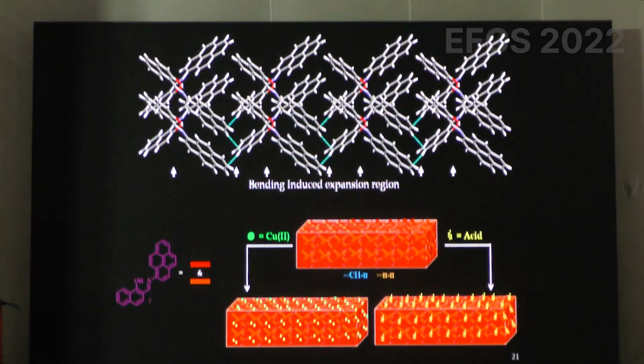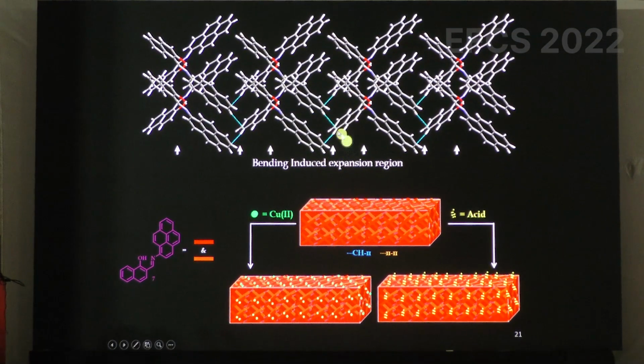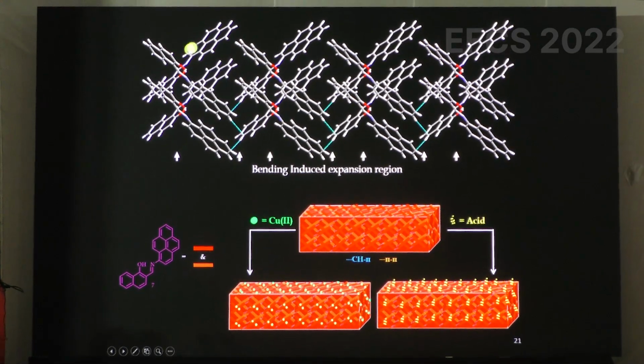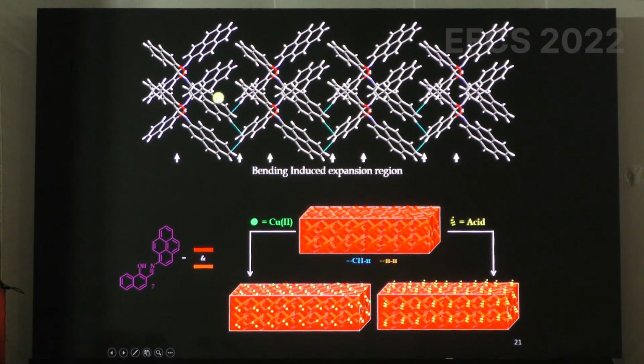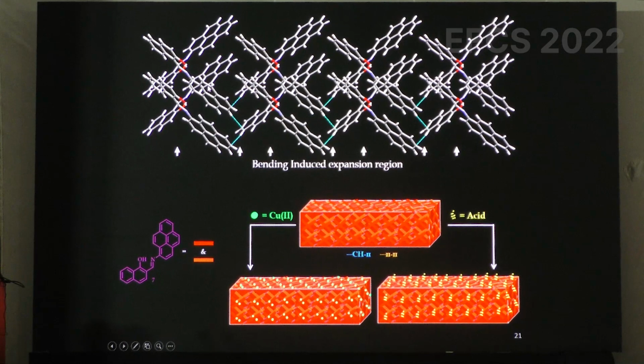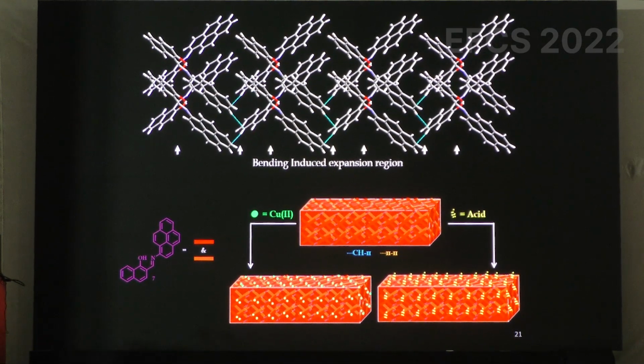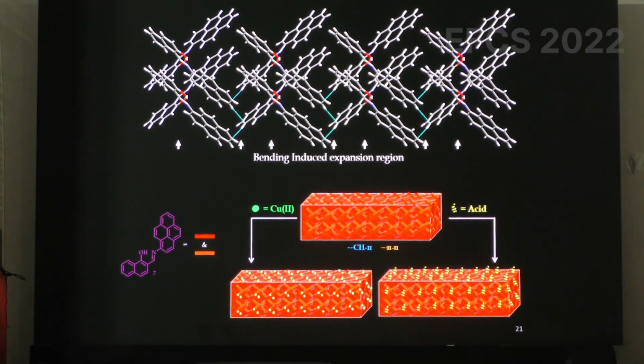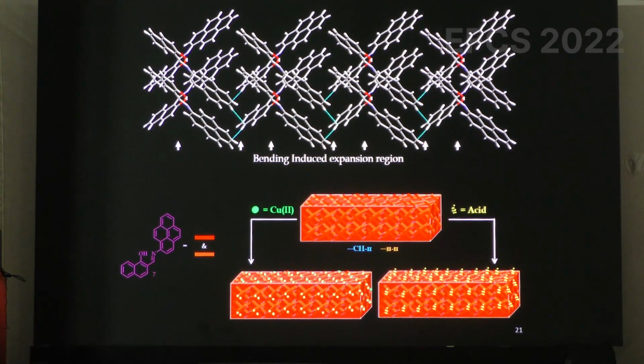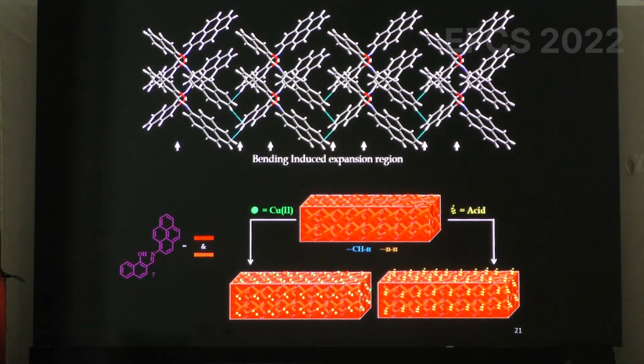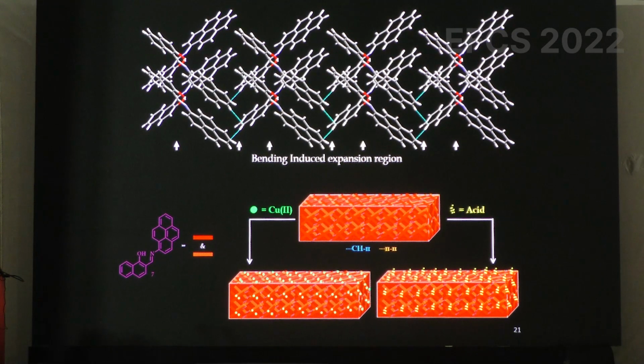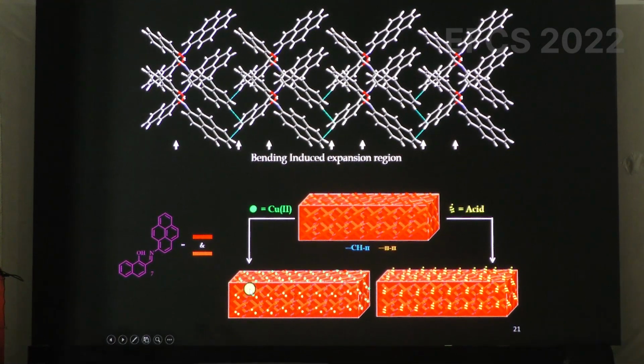So this is again the crystal packing, and you can see from this crystal packing, this is one molecule, this is another molecule of this compound. They have an interlocking kind of structure, and in between there is a void or a cavity where probably the metal ion and the acid can bind. So we assume that this is a surface modification, and when you dip the crystal into a solution of copper, the copper gets deposited on the surface. That's what we are showing here.